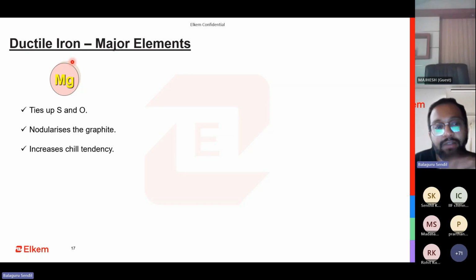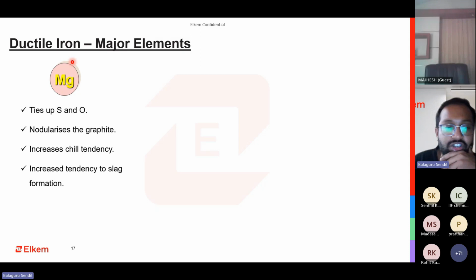That is why, if you are adding more magnesium, if you are having a 500 kg treatment size, and just to save on cost, instead of using a 6% magnesium, you go for a 9% magnesium and reduce the addition percentage, you are actually using more magnesium, which goes free into the metal, which is not helping in creating this nucleating site, and can cause a lot of chill. That is why after magnesium treatment, you see a lot of carbidic structure in your microstructure.